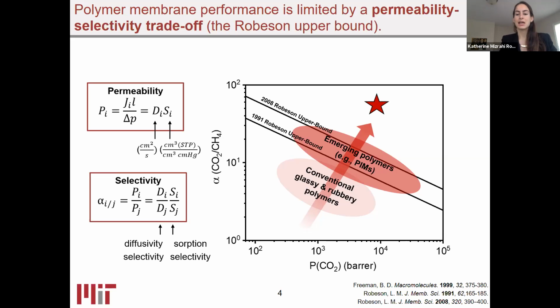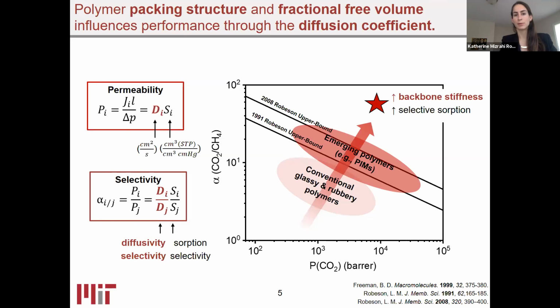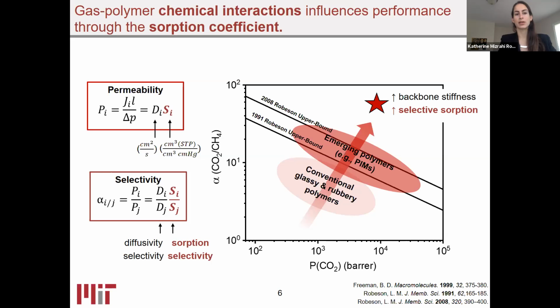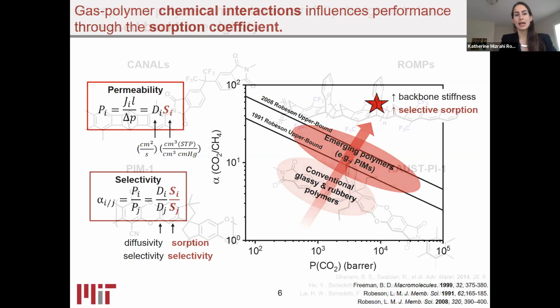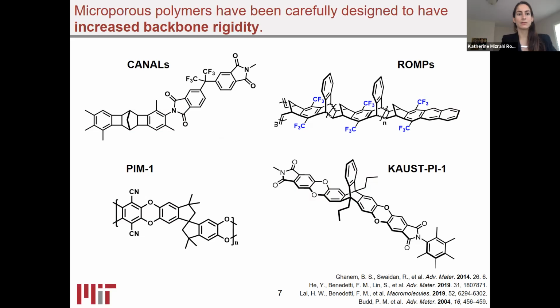In 1999, Professor Freeman developed a theoretical basis for this upper bound plot. And in that paper, he also suggested two key metrics or key synthetic considerations that could be used to improve permeability selectivity combinations. And these included backbone stiffness and selective sorption. So on one hand, backbone stiffness can be increased in order to change the polymer packing structure and increase fractional free volume. And this can influence performance through the diffusion coefficient. Whereas on the other hand, by tuning selective sorption or the gas polymer chemical interactions, we can influence performance through the sorption coefficient. And many researchers, especially synthetic chemists, have looked at developing new materials to have increased backbone rigidity.